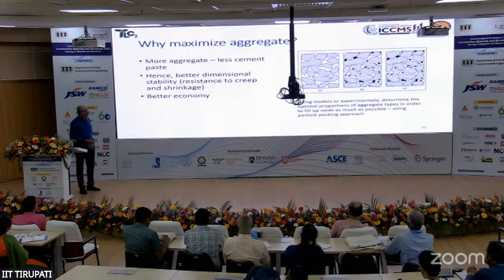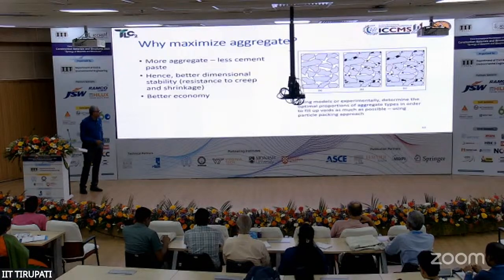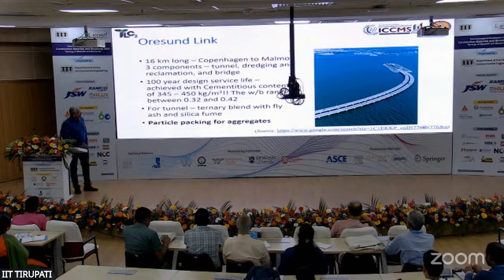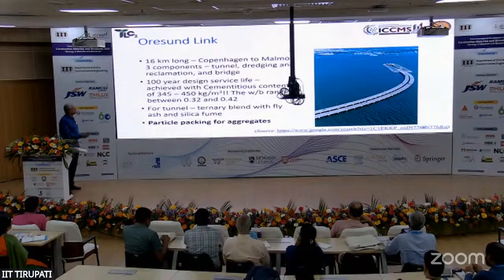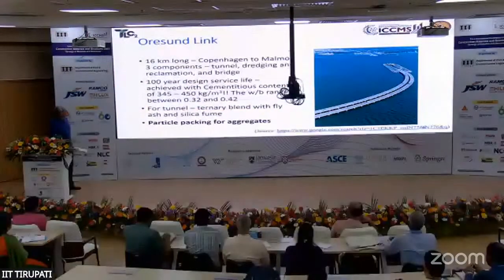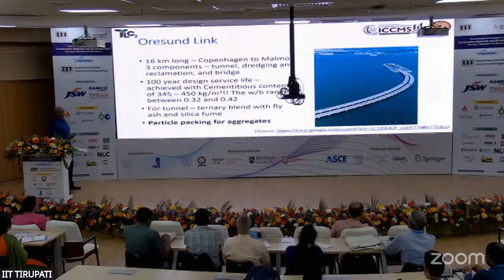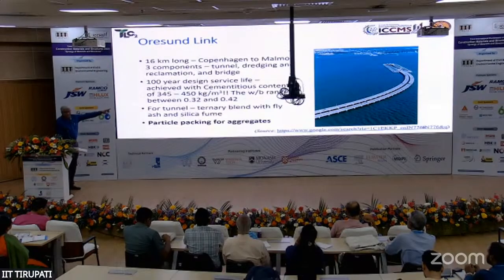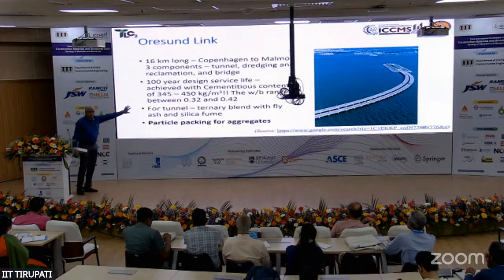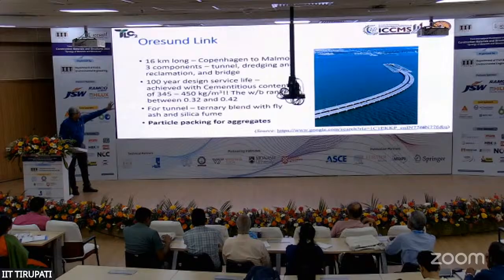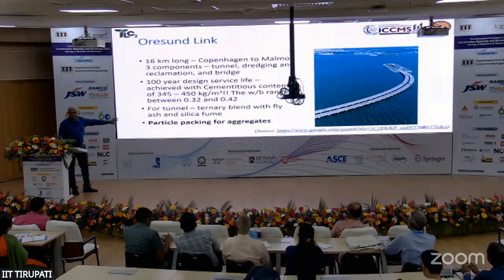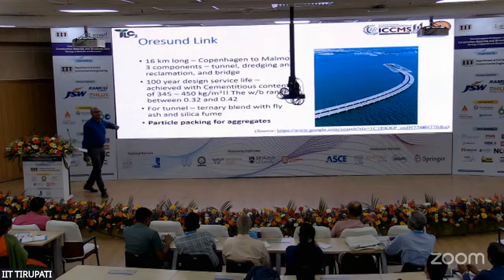It's a very simple approach to follow for mixed designs, brings about better economy. And of course, because you're having greater amount of aggregate in your system, it gets better dimensional stability. Now, this example from Sweden and the bridge tunnel system connecting Sweden to Denmark between Copenhagen and Malmo. This has a tunnel, dredging and reclamation and a bridge. It was designed for a 100-year service life. And note that all of this was done at total cementitious contents of well less than 450 kilogram per cubic meter. Here, they had used the particle packing system to bring down the need for large amounts of cement.